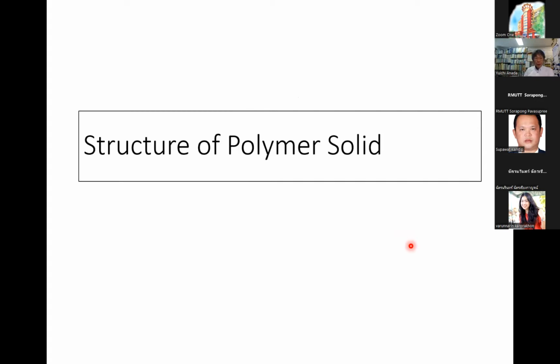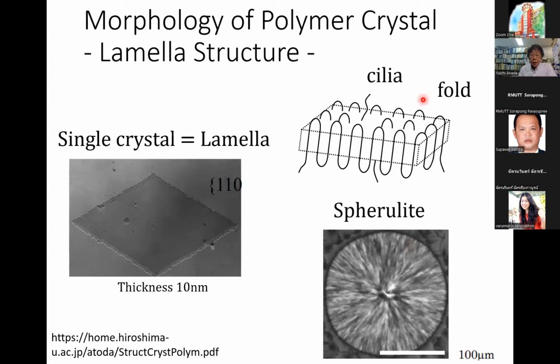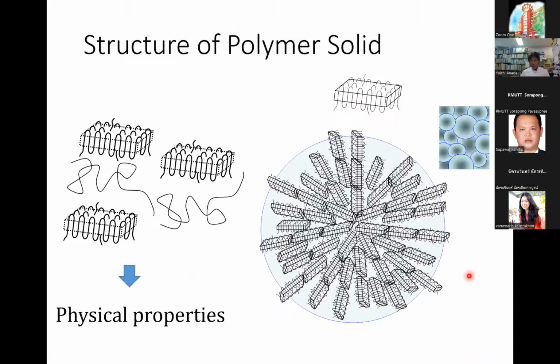I don't have much time, so very shortly I introduce the structure of a polymer solid. Some polymers make crystal, as I explained. Polymer chains make crystal, so in such a structure there is a surface area and a core area. The surface area is composed of the folded part of the polymer. This structure was found by electron microscope photograph. This is a spherulite. Such crystal units, crystallites, come together and make a big material. This is a spherulite, and this small part is a crystallite. We call it lamella.